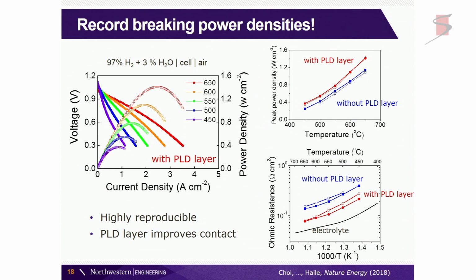And we did show that having this thin layer is important for increasing the power density. So our peak power density, that's the point right here, is increased by having this thin PLD layer. And we could also see that it was impacting that ohmic resistance and therefore what we view as the contact resistance. So that's where we're seeing that significant benefit. And we make sure to do multiple samples. We're not chemists who are stuck with just a few milligrams, as was mentioned earlier. We can make large-scale samples and do this multiple times and see it's quite reproducible.